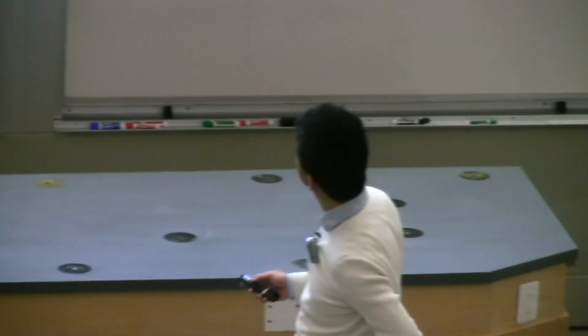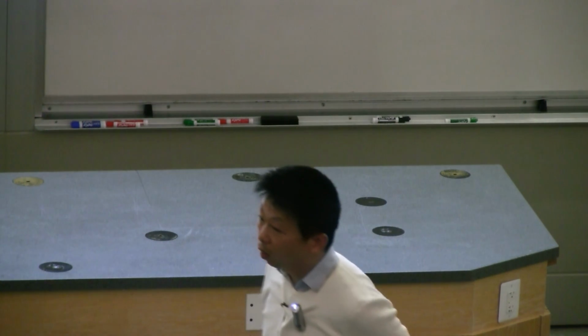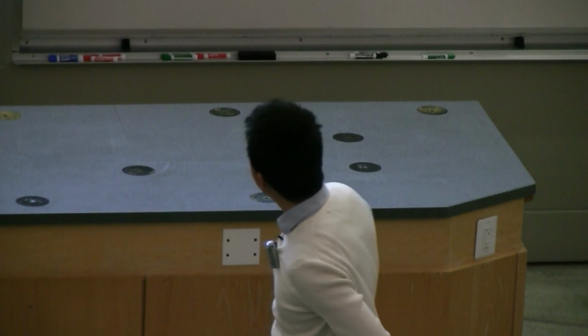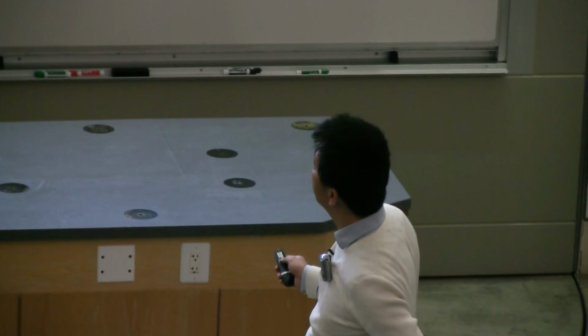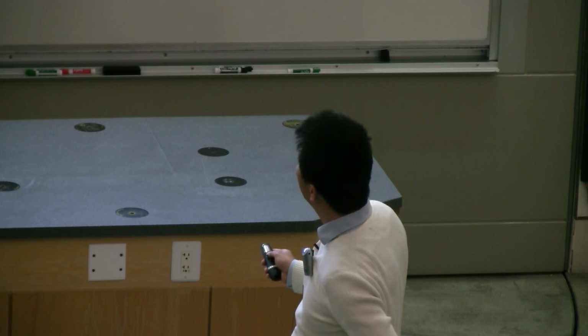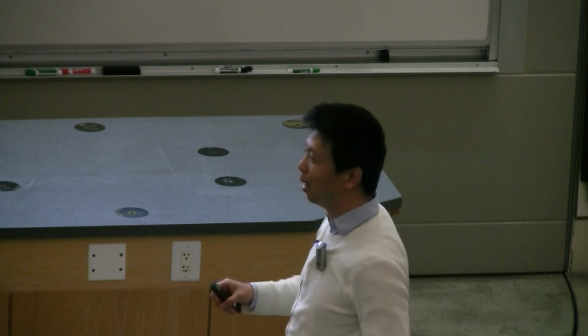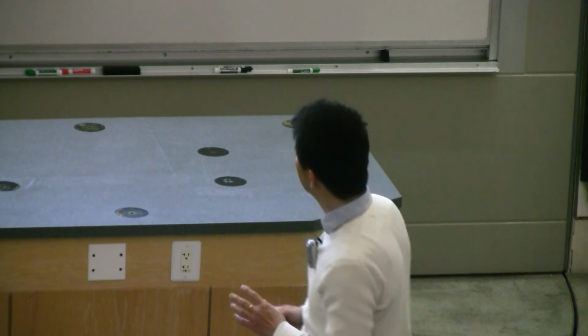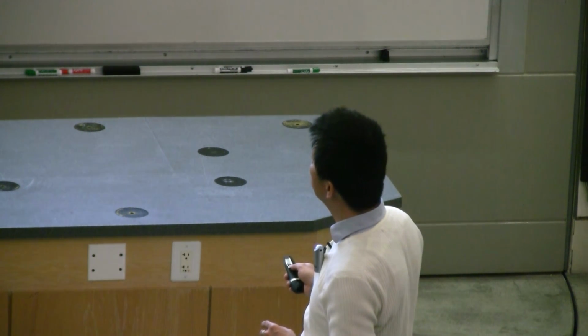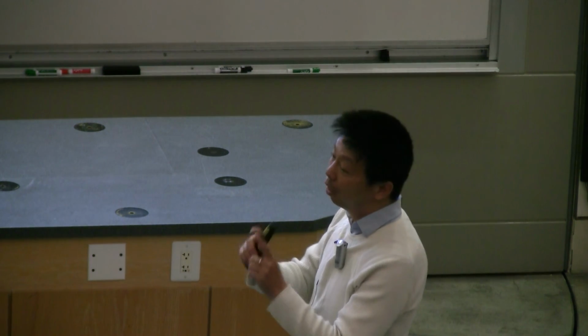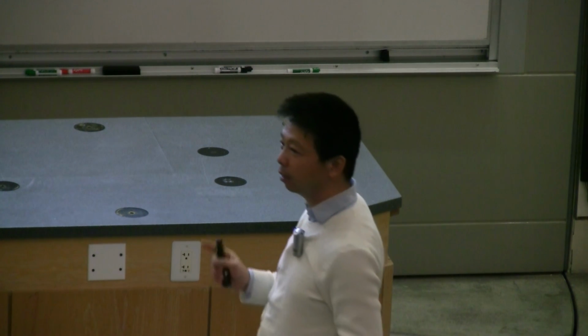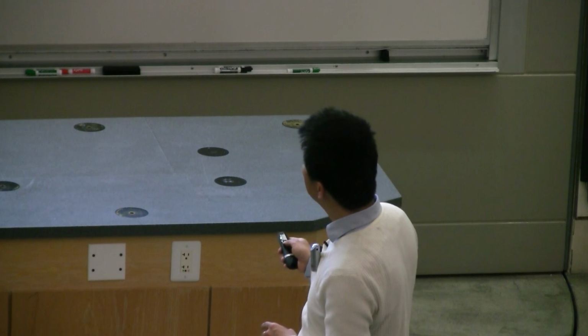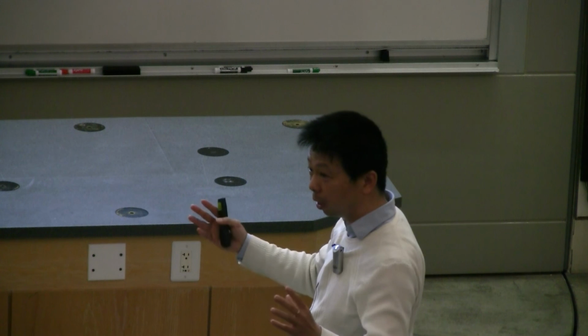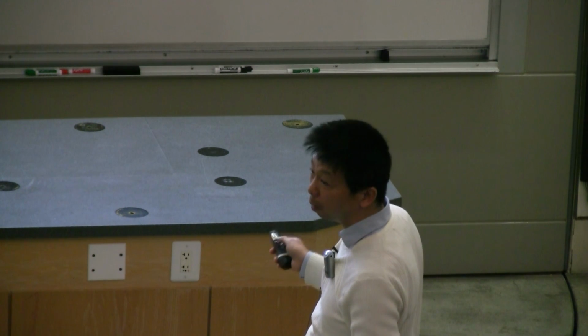You sort of indicated that all of these things are in their smallest spin state. Do you ever get them in an excited spin state, like a spin 3/2 trion or a spin 1? If you have spin 3/2, basically they cannot form a bound state anymore, at least in this regime. Liangfu actually has some calculation if the electron and the hole mass are very, very different. In that case, it's actually possible to form a trion even when the two very heavy holes have the same spin. When the electron and hole mass are comparable, the theory calculation shows that if the two holes have the same spin, the lowest energy state is not a bound state. But if they have opposite spin, you can have a bound state.